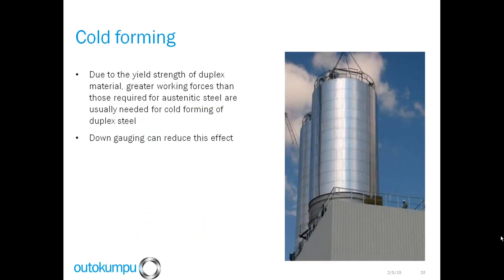We look at cold forming. It's going to be similar to some of the other forming we talked about. You're going to end up using larger radii to bend things. Again, more spring back for a certain thickness when you compare it to 300 series stainless steel. So you're typically going to require more power when you do cold forming of duplex stainless steel.